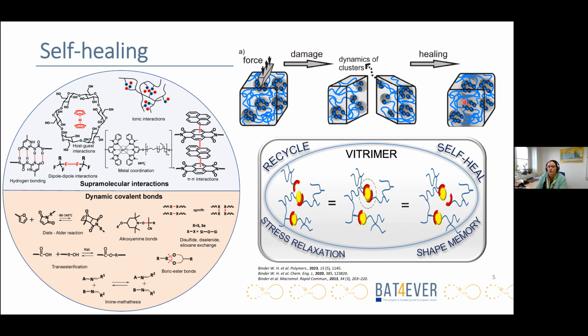The most important factors influencing the supramolecular interaction and subsequently the self-healing are the strength of the interactions. That means that depending on the kind and the number of the interactions, we can have either a stronger or weaker supramolecular network. And of course, also the dynamics of the self-healing process is important. That means how fast these non-covalent bonds are rearranging, opening and closing again after the damage.